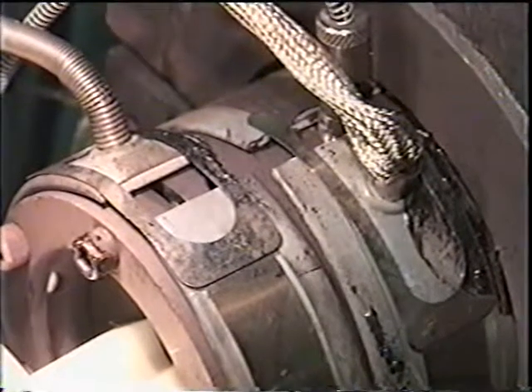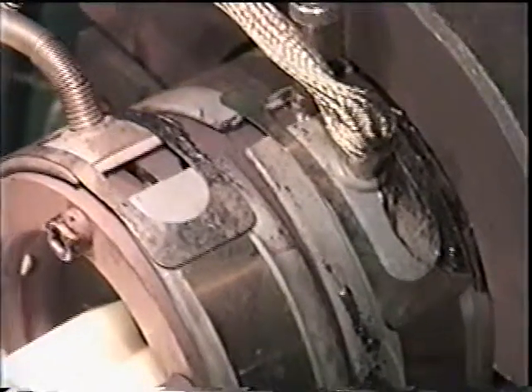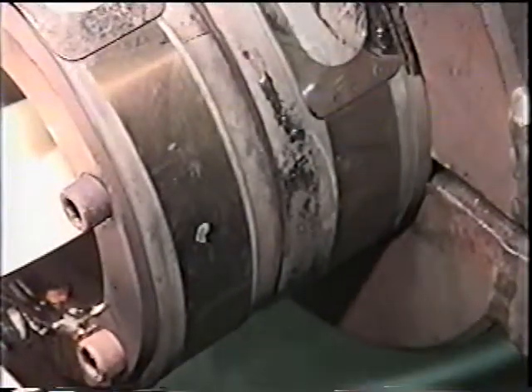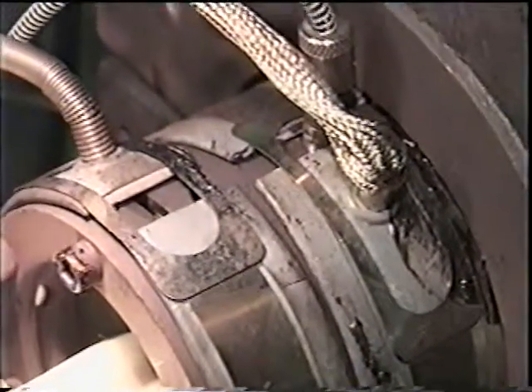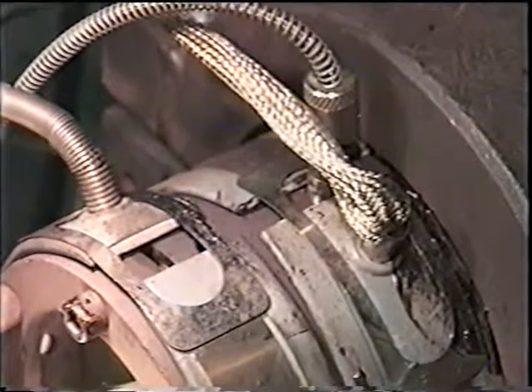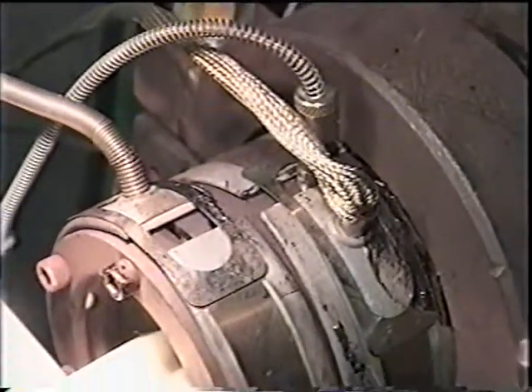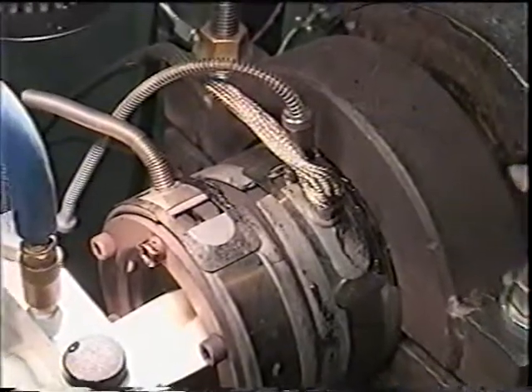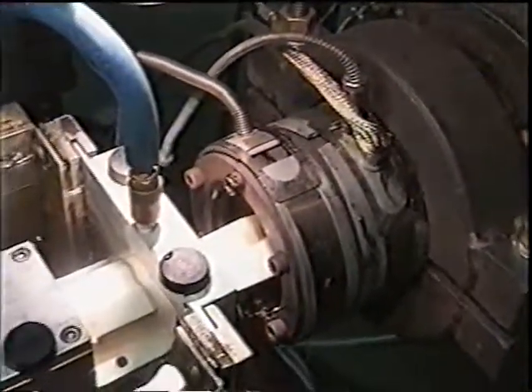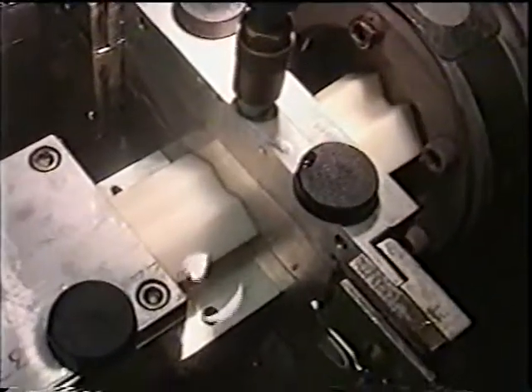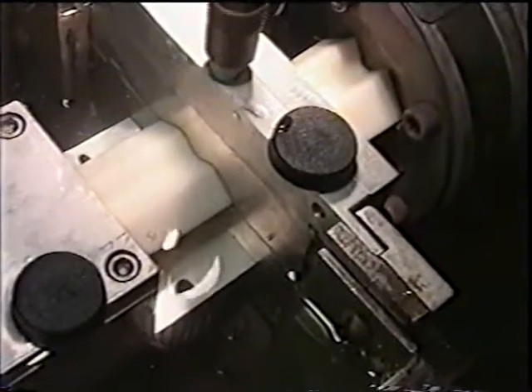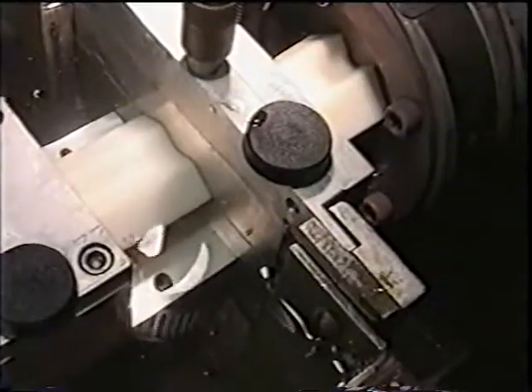On the die, we use heater bands to help bring the temperature up on that piece of metal. And we also use thermocouples, which help measure and monitor the temperature of the die. From the die, it's actually going into a sizing plate in the fixtures. For this particular job, this set of plates and fixtures involves a vacuum system. This die design has vacuum ports coming up through the plate.